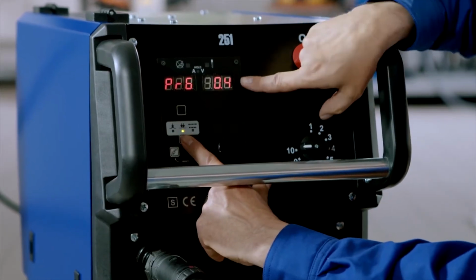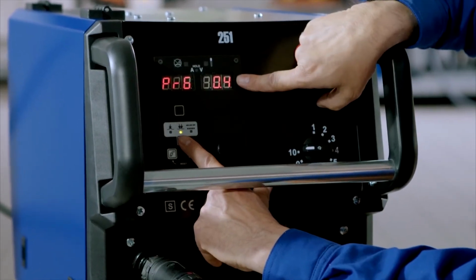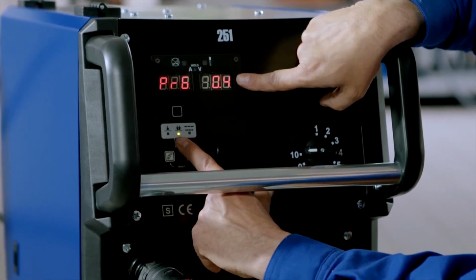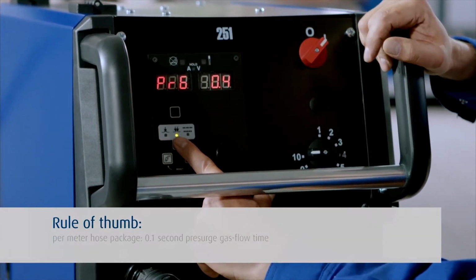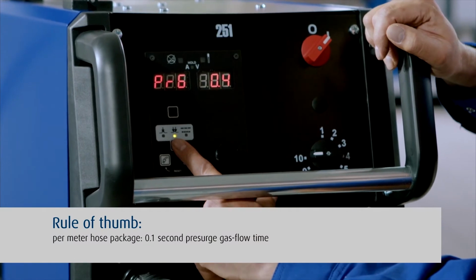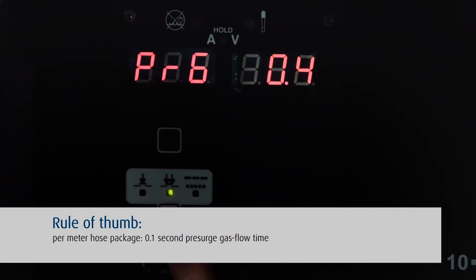Next, we are going to set the gas pre-flow time. You may be wondering why we need to do this. Quite simply, this setting prevents pores from forming. We recommend that you set 0.1 seconds of pre-flow time per meter, or 3.3 feet of hose assembly. If you're using a 4-meter assembly, for example, we recommend a pre-flow time of 0.4 seconds.